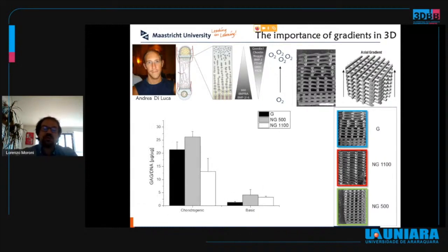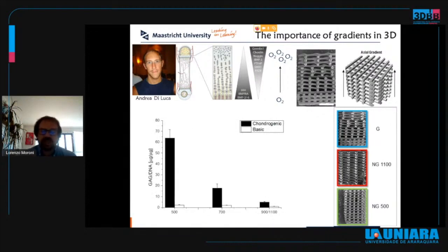Vice versa, if we now look at the same sort of study, but in chondrogenic media, we would see an increase of GAG, or glycosaminoglycans, production, both in this case for gradient and non-gradient scaffolds with the smallest pore size. And again, if we look at the gradient scaffolds and cut them into the different segmental units, we would see such an increase being inversely proportional to the pore size. So highest with the lowest pore size used in the scaffold fabrication, again in the order of 500 microns.